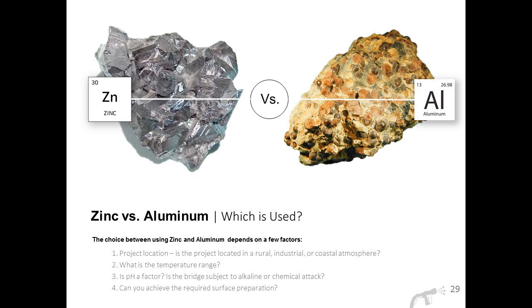So what's important to remember is metallizing is used outside to protect bridges. So it really only needs to handle temperatures from, again, minus 30, minus 40, minus 50 at the most in Fahrenheit, up to maybe 120 degrees Fahrenheit on the hot end. This is where this distinction comes into play, because as you add aluminum, it's able to resist much higher temperatures that you would see in, for example, furnaces and boilers and things of that nature. So zinc and aluminum are certainly both viable options for the bridge industry, but again, keep these temperatures in context as we go through some of these materials more specifically.